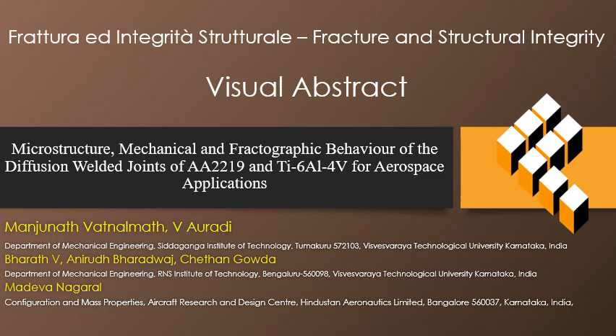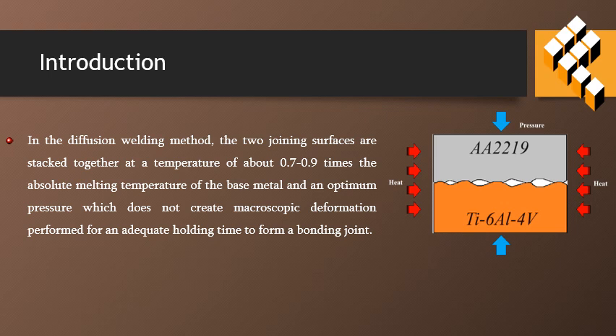Our study entitled Microstructure, Mechanical and Fractographic Behavior of the Diffusion Welded Joints of AA2219 and Ti-6Al-4V for Aerospace Applications. In the diffusion welding method, the two joining surfaces are stacked together at a temperature of about 70 to 90% of the absolute melting temperature of the base metal, and an optimum pressure is applied for an adequate holding time to get the diffusion welded joints.